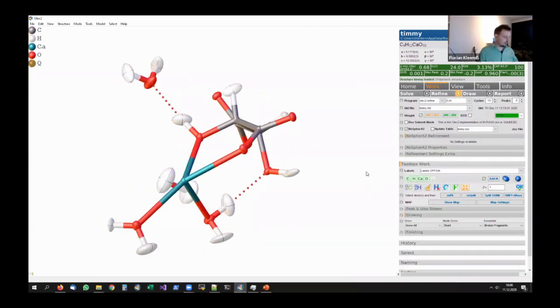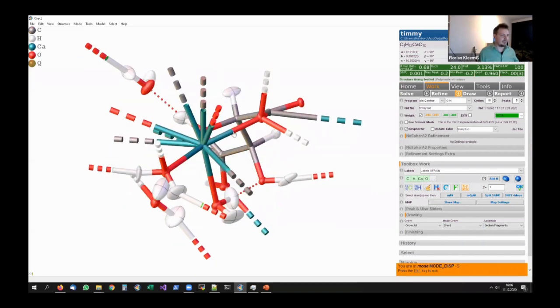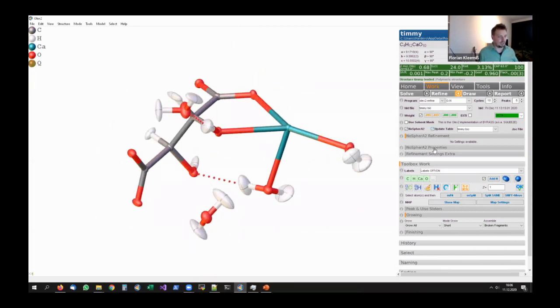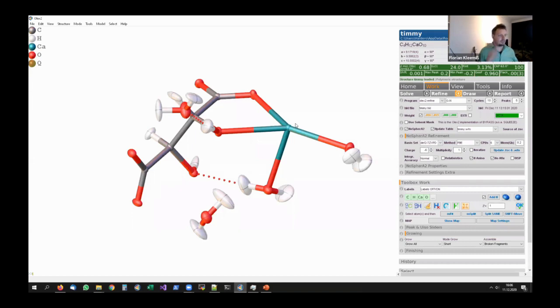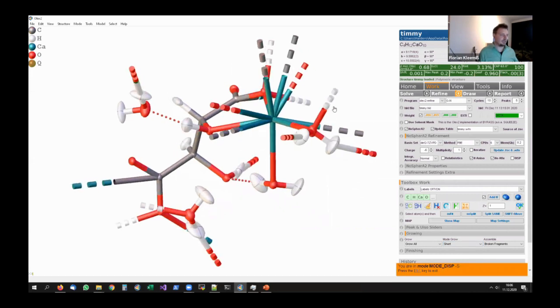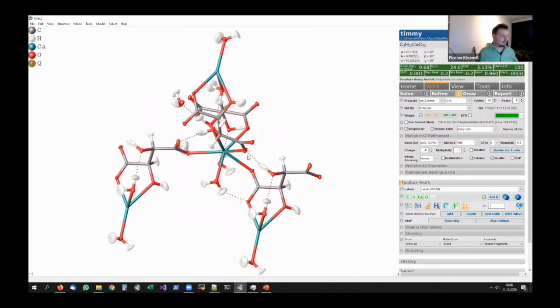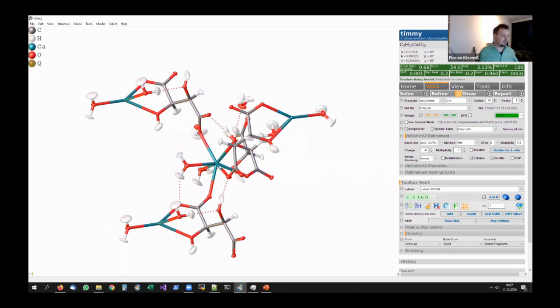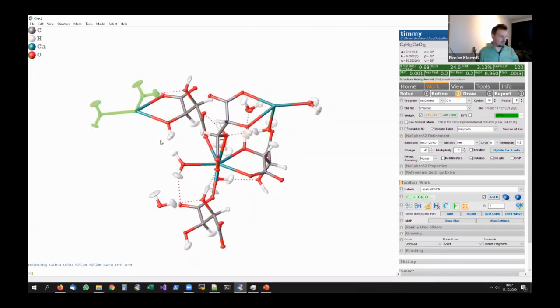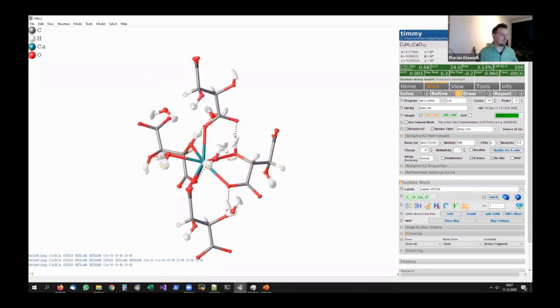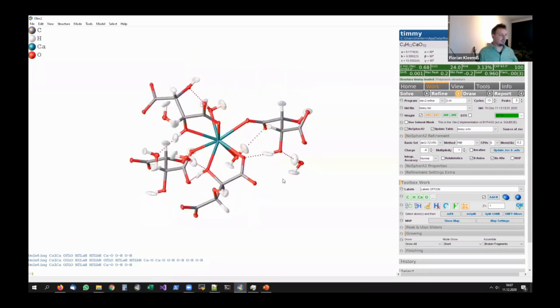And in this case, when you think about it, I think it's a calcium ion in the middle, surrounded by more molecules. So if I would calculate the wave function only on the asymmetric unit, which is neutral in charge, this would not be the correct model because the calcium would lack interaction partners on some side. So what you have to do is grow the cluster to fully have the coordination sphere for the calcium. But then you think, okay, this calcium is the asymmetric unit one. So this one is going to be used in my refinement, while the information on these two calcium atoms is maybe not as interesting to me. So I can delete them from my cluster that I grew and simply use the calcium of the asymmetric unit.